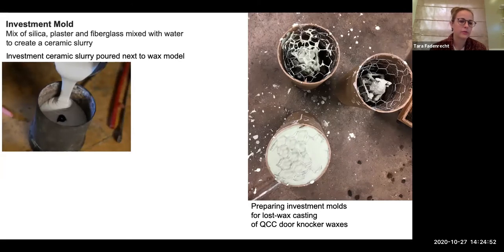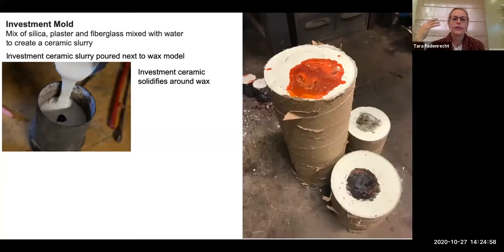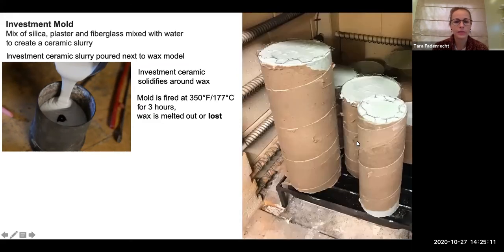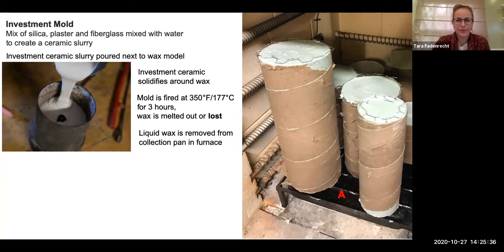So here's kind of the process of what you would do next. Pouring along the side of the wax model, not directly above it. That slurry solidifies in about 20 minutes. And you can see at this point, the paper tubing has been removed. We can see the bottom of the pouring cup that we saw on the other piece. And then it goes into the furnace. And this is where we get the lost wax cast name from, is that as it's heated for 3 hours at 350, the wax is evacuated out through the bottom, and it's collected in a pan here, and that pan is removed, obviously, so we don't have a smoke fest inside the foundry.